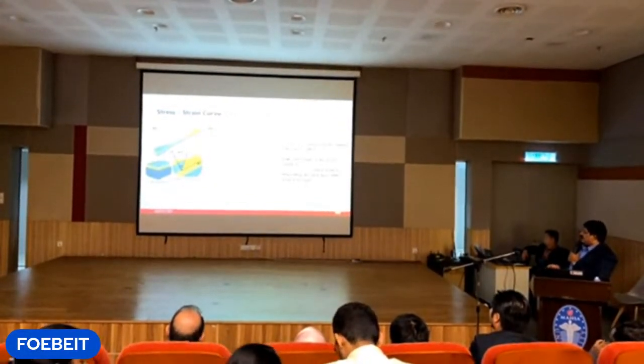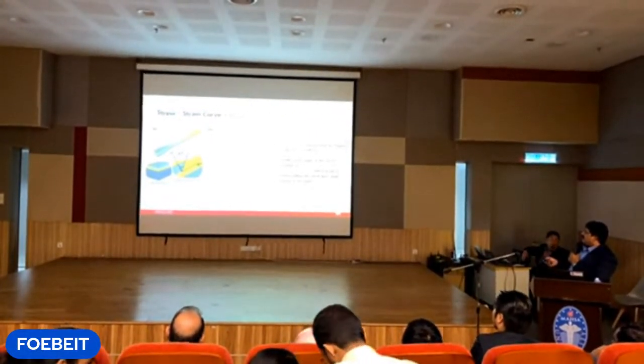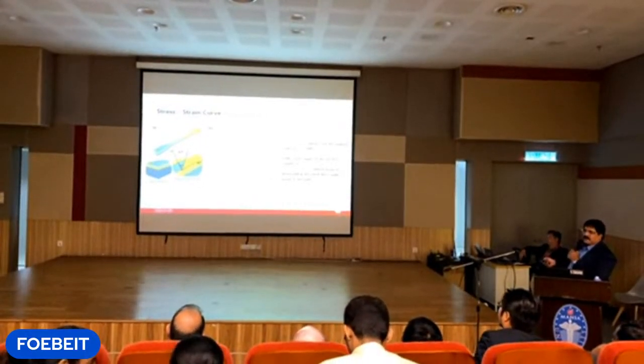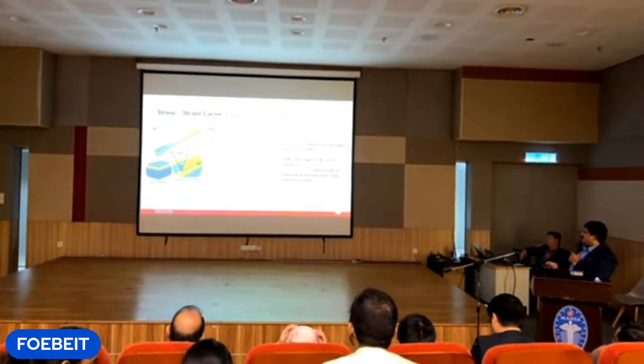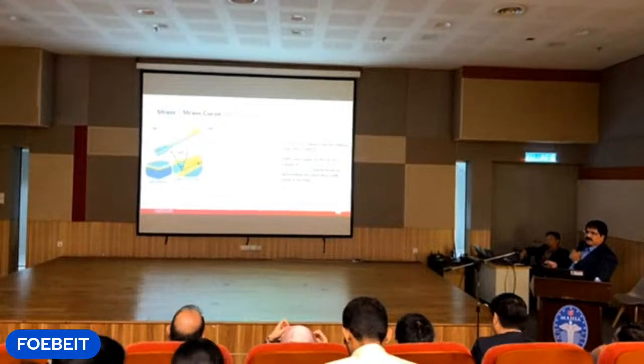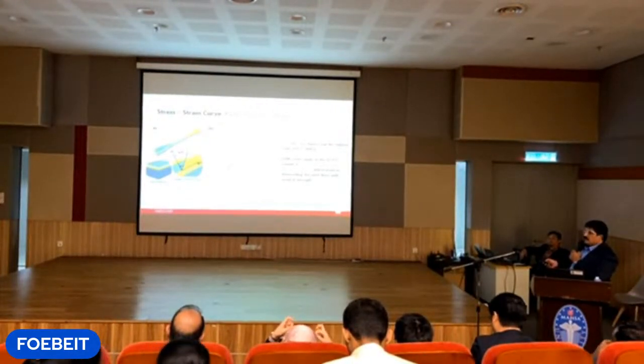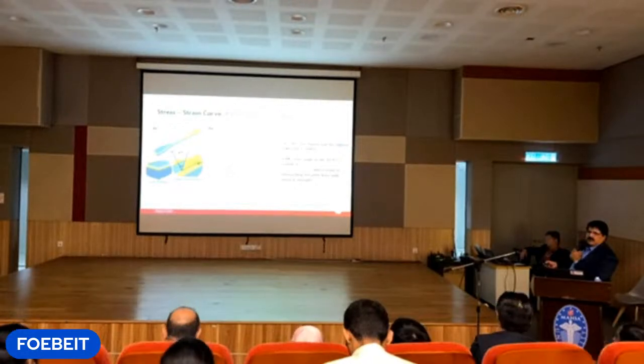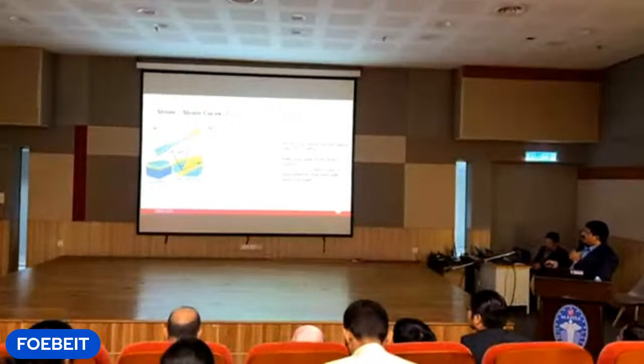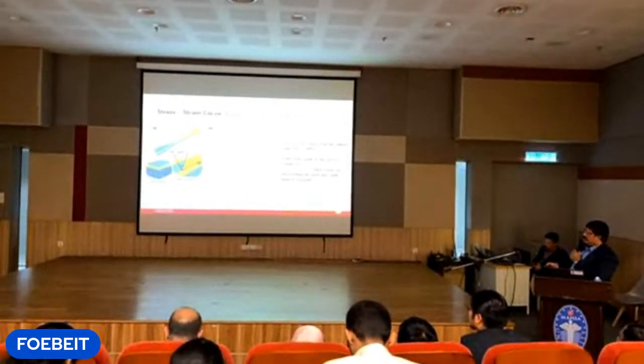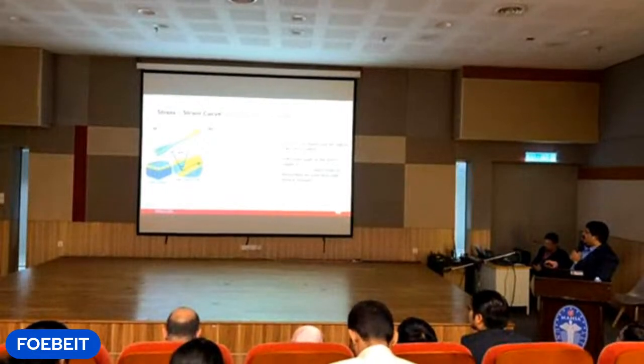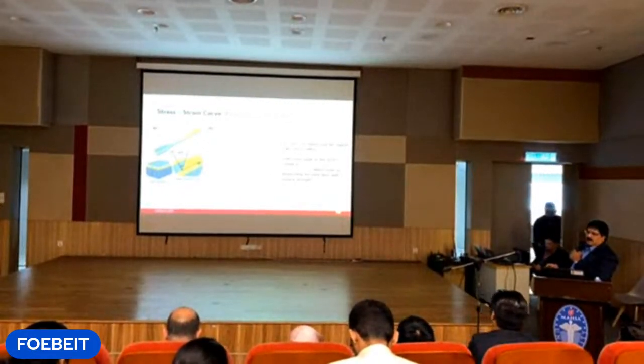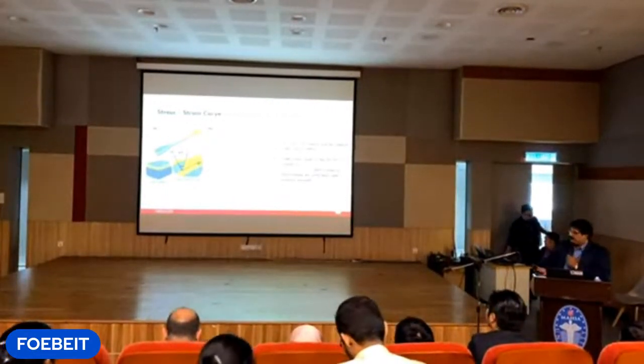So here you see the stress strain curve for the raster direction angle, that is the raster angle. At 0 to 45 degrees, it has low strength and is more brittle. And you see that at 90 degrees there is more strength, and the brittle nature is less when compared with 0 to 45 degrees. Okay, so it is the value for the different patterns like a raster angle.